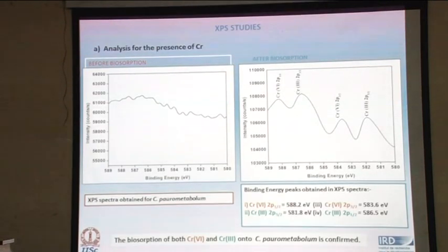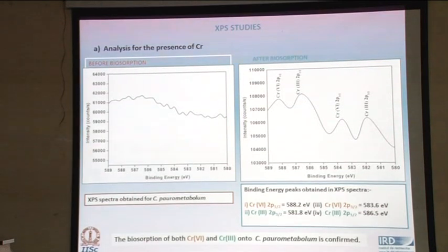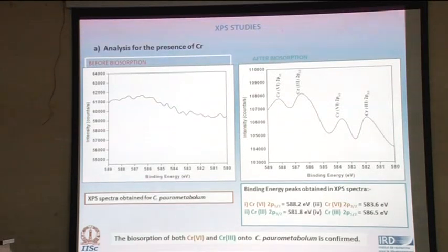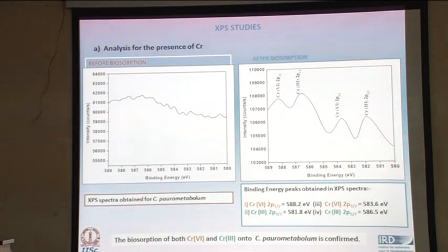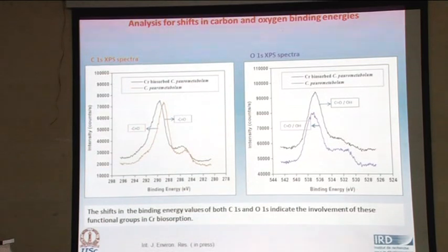What is interesting in the case of chromium is the two valency states that it exists in. We all know that hexavalent chromium is more toxic compared to trivalent chromium. So we wanted to know the remediation mechanism adopted by the microorganism. So we did some X-ray photoelectron spectroscopic studies, and we could identify not only chromium 6 but also chromium 3. And you can see here that the binding sites on the microorganism with respect to the chromium are both the carboxyl groups and the hydroxyl groups, where you see there are binding energy shifts after this interaction with these metal ions, indicating they are involved in the coordination or chelation of these metals.